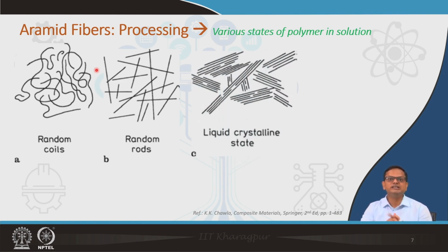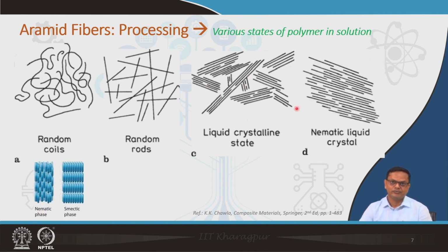of liquid crystalline state. So, you can see here a number of random rods come together, come closer and make this kind of zones, okay, of liquid crystalline zones. Okay. So, this kind of alignment takes place in the presence of H2SO4, and finally, what happens with these regions is that ultimately you get this kind of nematic liquid crystal structure.